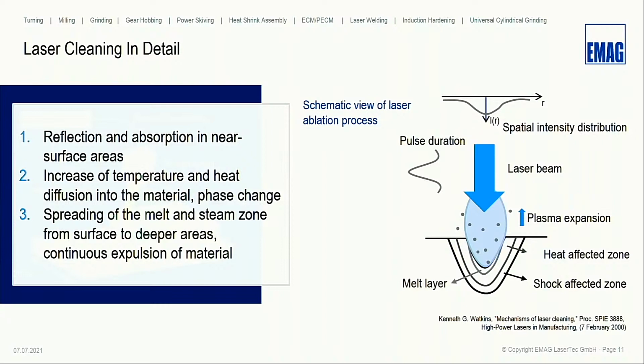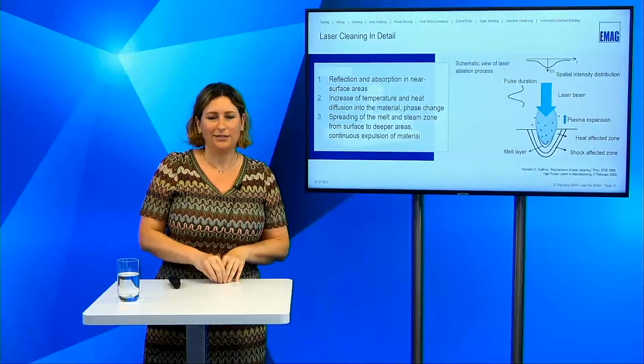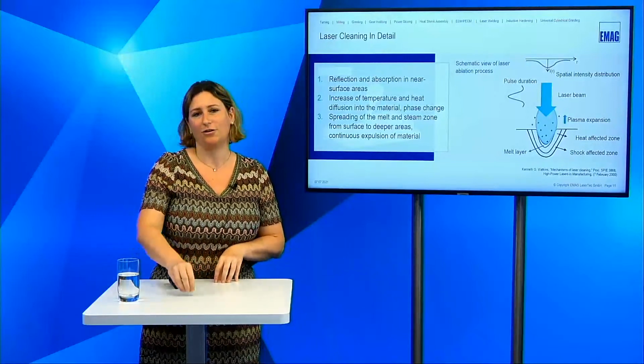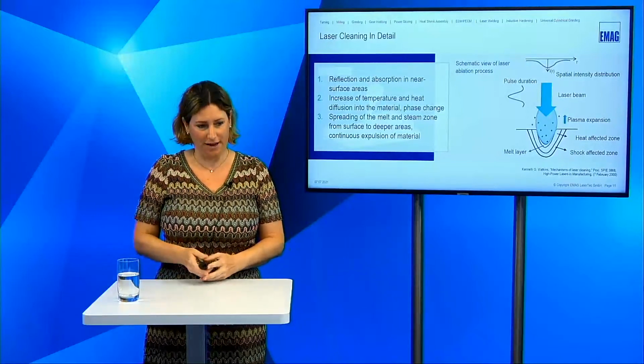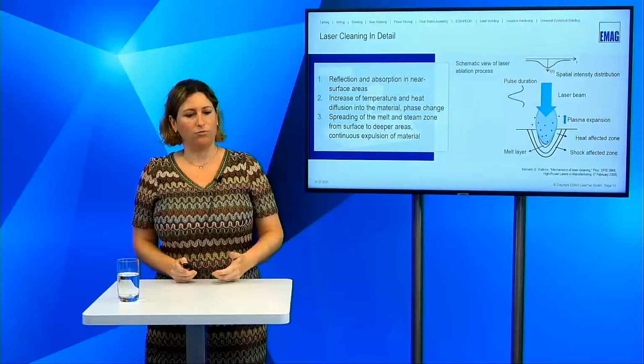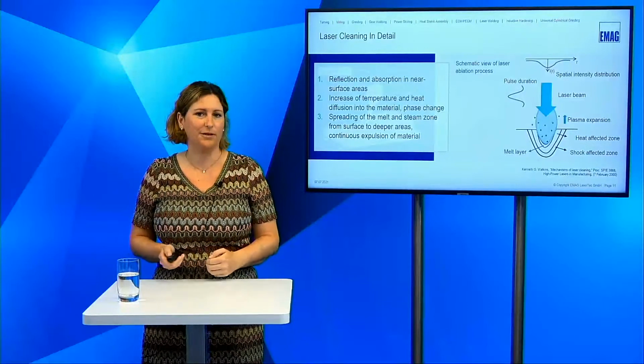But this sounds very slow when I explain it. The time between hitting the surface and vaporization is really short, because the pulse durations are really short. You have only nanosecond pulses, thus the interaction time between laser beam and surface is just billionths of a second, as I already said. And thus the time between hitting the surface and removing the material is also a billionth of a second. So it's really fast, and that is the reason why you don't hurt the surface of the sample that much.